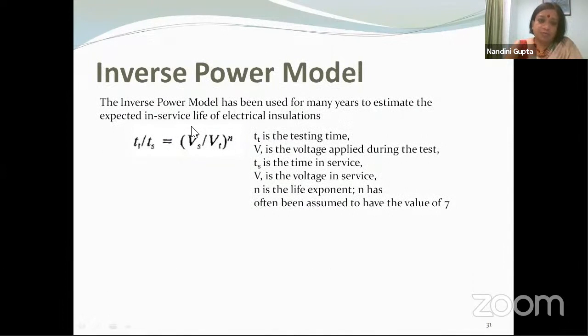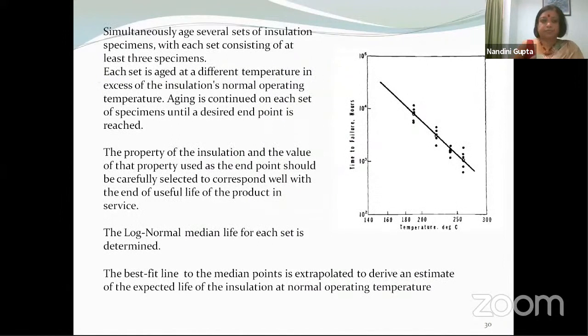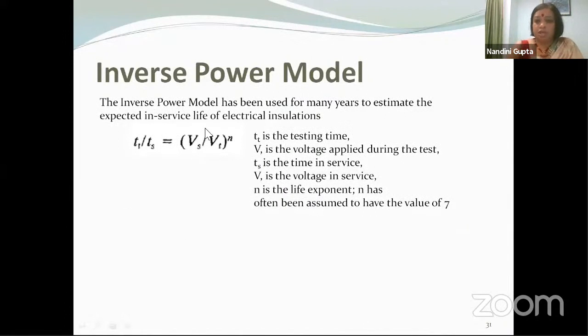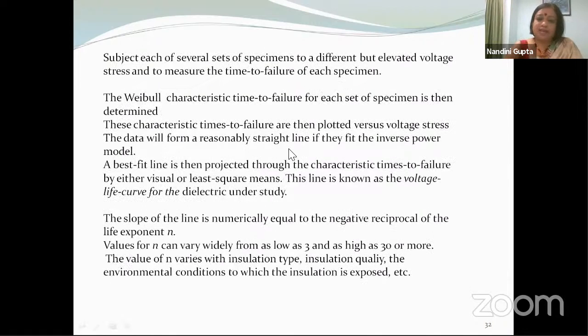Apart from the Arrhenius model, we also have the inverse power model. We have the inverse power model, which is most often used to estimate the in-service life of electrical insulation, where we have the ratio of the testing time and the service time given as an inverse power law of Vs by Vt, where Tt is the testing time, Vt is the testing voltage, and Ts is the service time, and Vs is the service voltage. So often this exponent, which will have to be obtained using the data, is often assumed to have a value of 7.